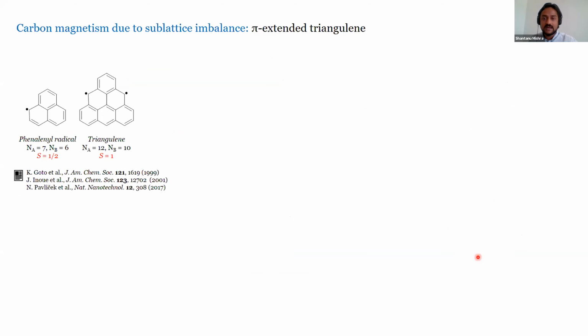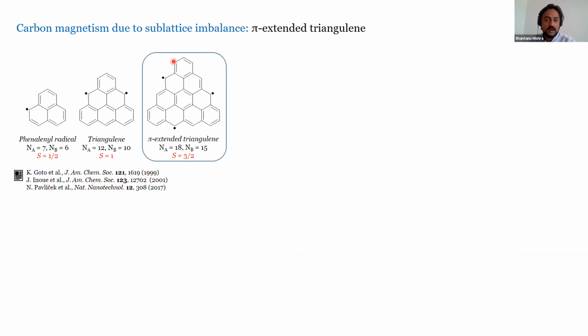And so with that, let me come to the rather simple case first, where magnetism arises as a consequence of sublattice imbalance. And we are going to talk about the family of triangulenes, and the smallest 2 members are shown here. Now they're interesting because, of course, as you increase the size of these molecules, the sublattice imbalance increases, and consequently the total spin increases. So it always ends up giving you high spin graphene fragments. And so this triangulene was published in a seminal work by Leo Gross and colleagues at IBM Zurich in 2017. And we wanted to explore a larger member of this family and understand if we can see some form of spin correlations directly with the STM.